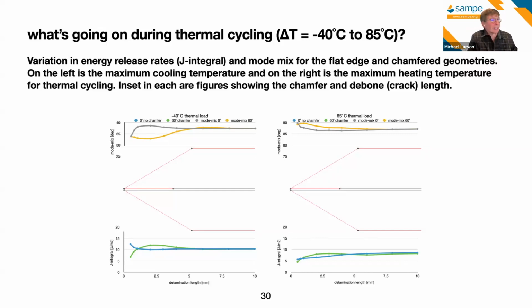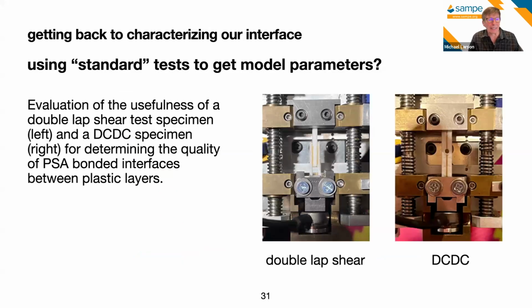And then in the bottom is what is the J integral value for these? And it is interesting for very small delaminations, something that you would miss in manufacturing and production in your inspection, perhaps, that in the lower left, we see we do kill the driving force for very small initial, say, inclusions that might be there, insufficient bonding that can occur at those edges because of particles or maybe oil, that you can actually inhibit the development of these failures at the edge by judiciously doing that.